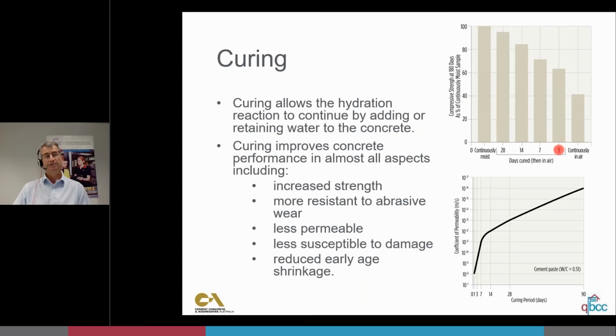If we cure it for 3 days, we're achieving over 60% of that strength. And if we cure it for 7 days, then over 70% of the strength. So you can see that curing process, that process of holding water into the concrete so the concrete can properly hydrate and gain strength, is pretty important.